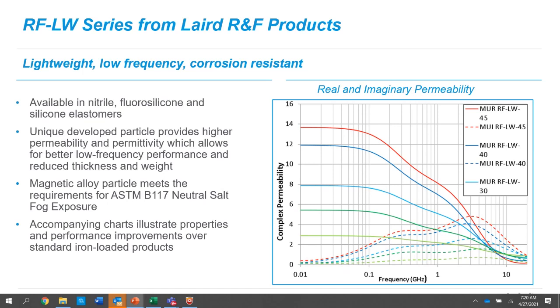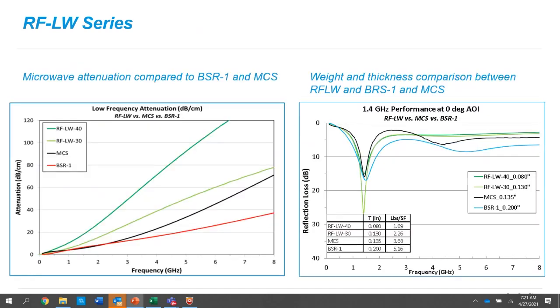And what we found is we've got a series of products which have a much higher permeability and permittivity than our standard iron products. So one, it's good for low frequency applications. Two, it weighs less because you use less of it. And three, it meets the ASTM B117 salt fog. So for low frequency corrosion solutions, we have a new answer, which we're releasing to people and getting a lot of interest in. And these two graphs show you a little bit of the advantages.